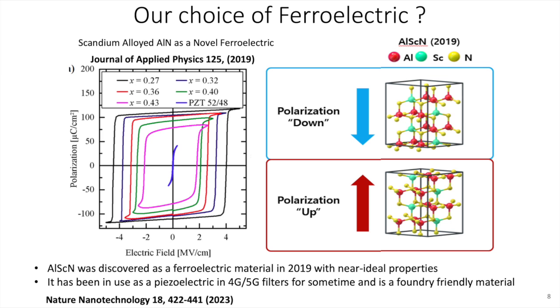So if it has piezoelectricity, there were some people who suspected it should also have ferroelectricity. And there were people searching for it, and the Germans in 2019 found that indeed it has ferroelectricity. That's the journal reference shown, from 2019 from Germany. I think it's Kiel University and the Fraunhofer Institute. They observed nearly ideal ferroelectric hysteresis loops with very large polarization.